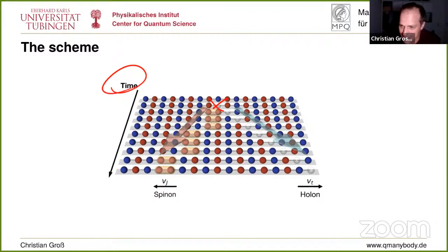By killing this atom, and we do that by shooting a laser beam, we are inserting a spinon and we are inserting a holon into the system. And now the idea is to track that spinon and the holon. Of course, the catch is that it's not so easy, especially for the spinons, because there are quite some spinons in the game. I showed you that correlation lengths are short, right?